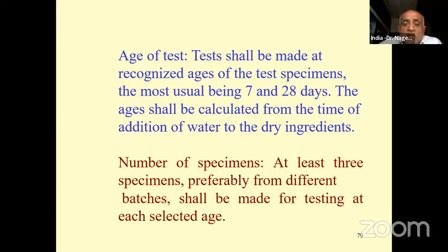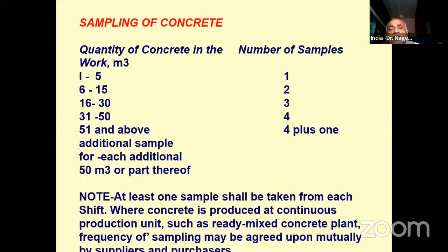So 7 and 28 days are normally the ages we check for most construction. And at least 3 specimens from different batches shall be made for testing at each selected age. So this is the sampling frequency: for 1 to 5 cubic meter, 1 sample; 6 to 15, 2 samples; 16 to 30, and so on. This particular table is applicable only for site mixed concrete. If it is RMC, it is different. For every 50 cubic meter of concrete supplied, we need to take 1 sample. What is 1 sample? 6 cubes. Why 6 cubes? 3 cubes for 7 days and 3 cubes for 28 days.